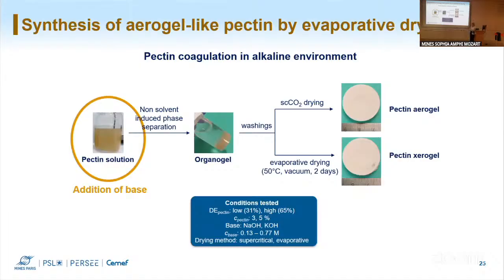Thing is that I'm not totally sure to understand the mechanism of formation of the gel. So we often see in literature that you can destabilize colloidal suspension somewhat by adding some ions. So and indeed, hence the Hofmeister series. But here, if you see actually a difference with NaOH and KOH with the same pH, so probably there's also an effect, as you said, of the contact between the ion and water, or the solvent might be also.